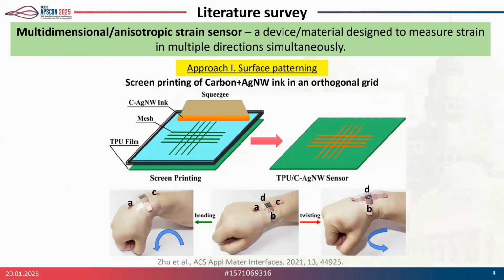There are basically two approaches for making such multi-directional strain sensors. The first one is surface patterning, and one of the methods is shown here, wherein carbon and silver nanowire is screen printed on a polyurethane substrate. As you can see, it was demonstrated that it can be used to measure the twisting and bending of a wrist. If you want to measure the bending of a wrist, you can measure the change in electrical resistance in electrodes A and C. And if you want to measure the twisting of your wrist, you can measure the change in electrical resistance along the B and D sensors.